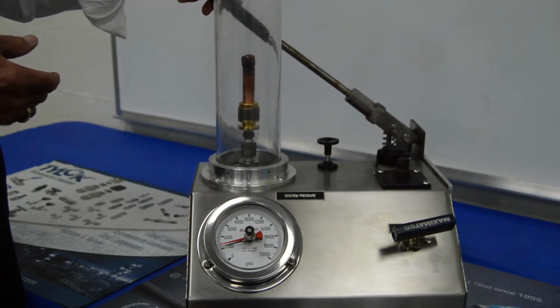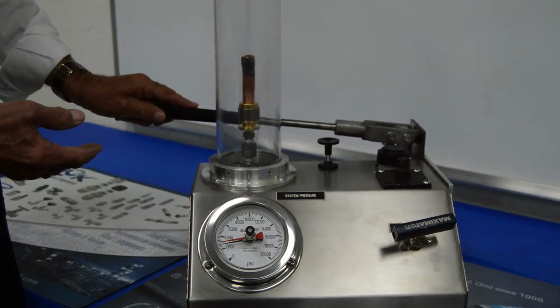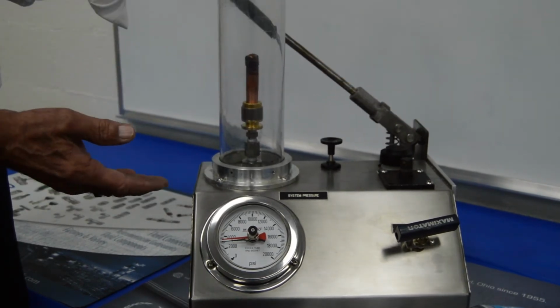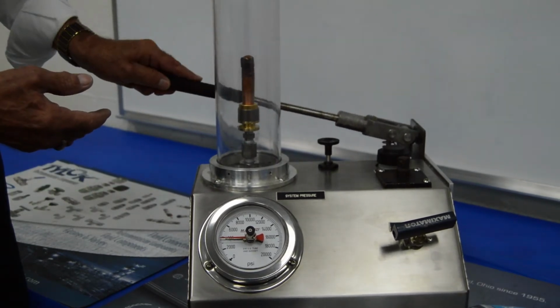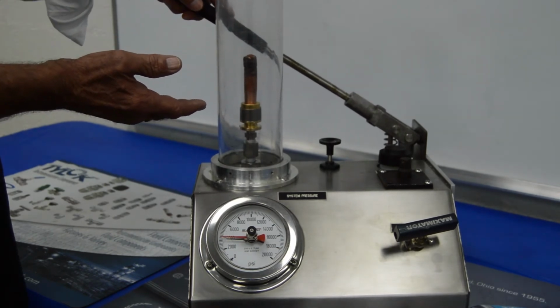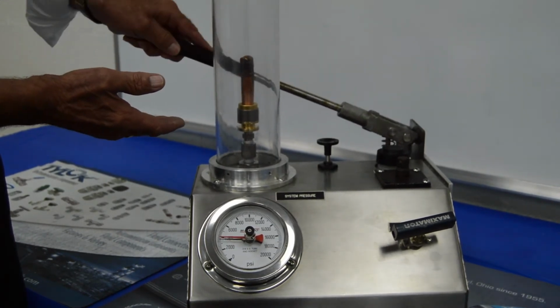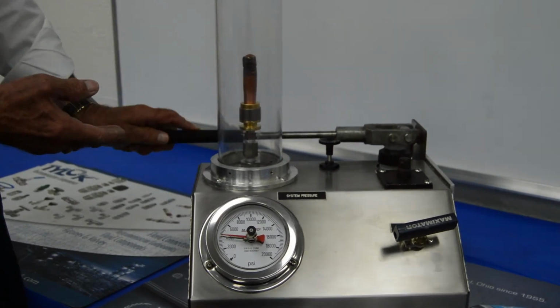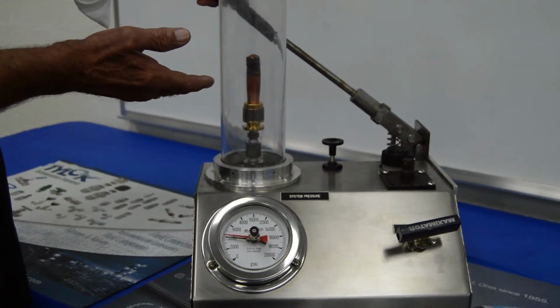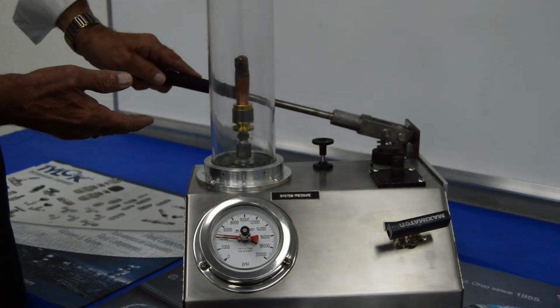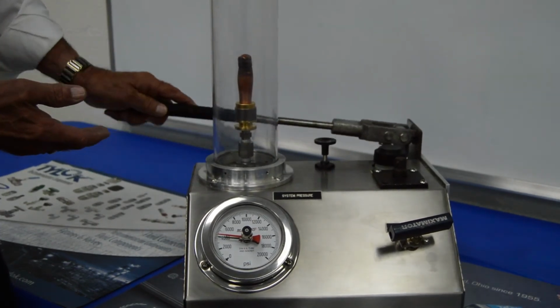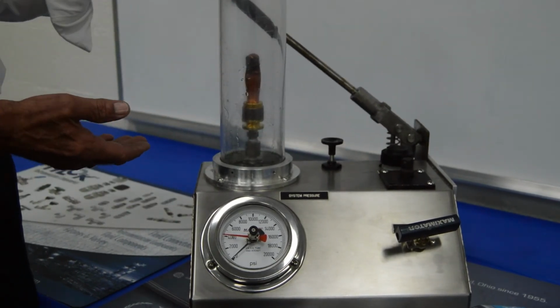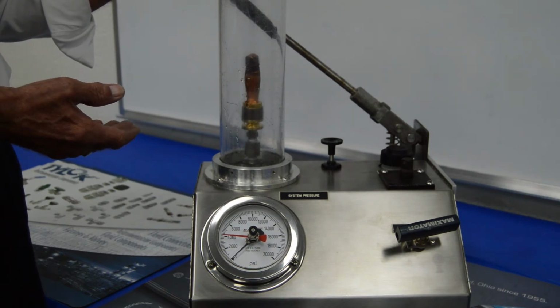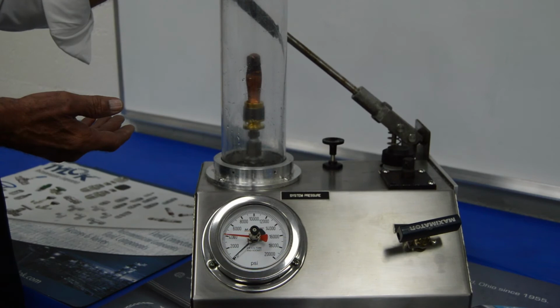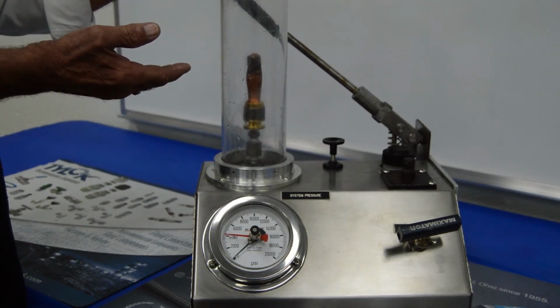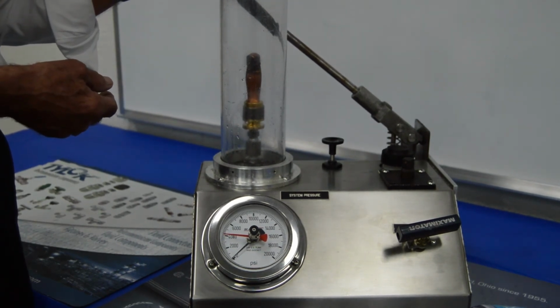We're now past the rating of the tubing as we approach 2000 psi, 3000 psi. You can see that the fitting is performing excellently without any leaks in the tube. You can see this, the tubing is starting to swell. And we achieved a burst at 4000 psi, over twice the rating of the tubing at 1682 psi. You'll notice that both the cap maintained its seal, and also the Medlok fitting maintained its seal onto this fully annealed tubing.